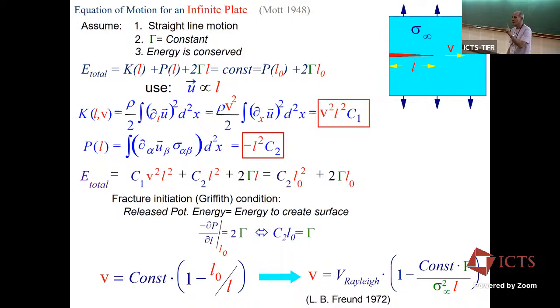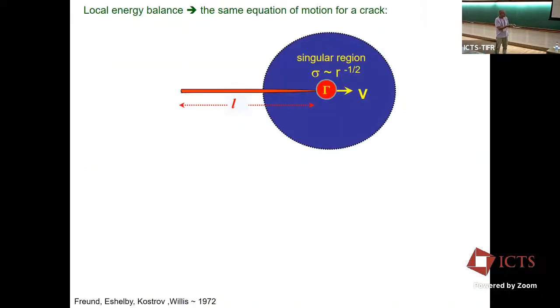They're the same thing, and I'll show you in a second. Okay, here we didn't mention anything about a singularity. There's no Griffith involved here. There's no stress intensity factor, if you like. But we can do the same calculation just here, because the only dissipation that's taking place is at the tip of the crack. So that's over here.